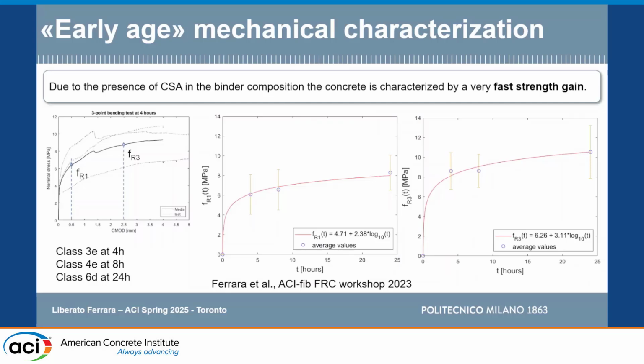But this is fiber reinforced, and one of the advantages of using this kind of mixes in tunnel linings is that you can completely eliminate the conventional reinforcement, which results in very great savings in construction time, and so on. And also savings, in some cases, in the quantity of reinforcement. But in order to do that, you must have fiber-reinforced concrete mixes which satisfy some performance requirements, which you can control with a three-point bending test according to the European standard.